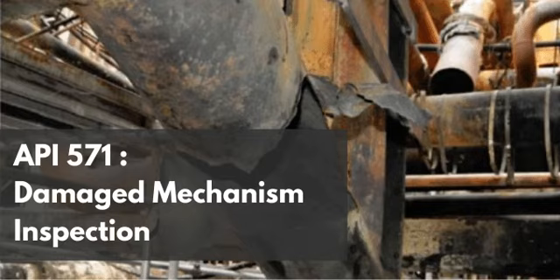The toughness is gone. Okay, I have to push back here on the mechanics of this, though, because this is where the logic seems to break down for someone actually walking the plant. Okay, let's hear it. If I have a piece of 446 stainless steel operating at 800 degrees Fahrenheit for 10 years, you are telling me the alpha prime phase has fully precipitated. Yes. The metal is fully embrittled. It has the toughness of glass.